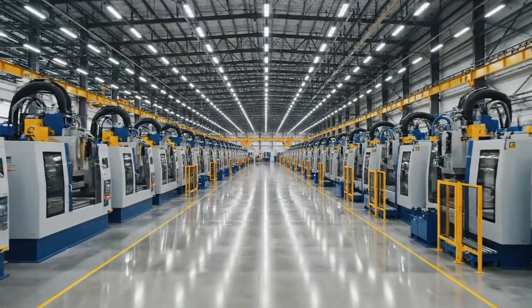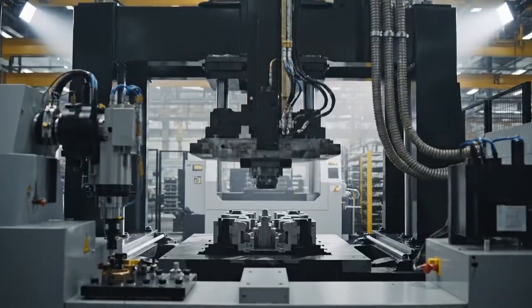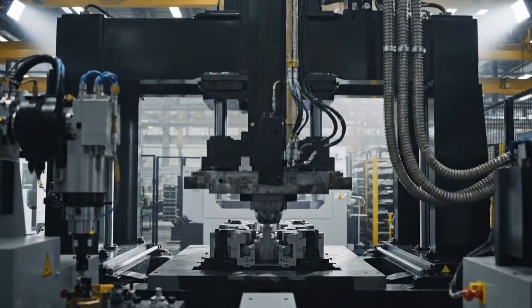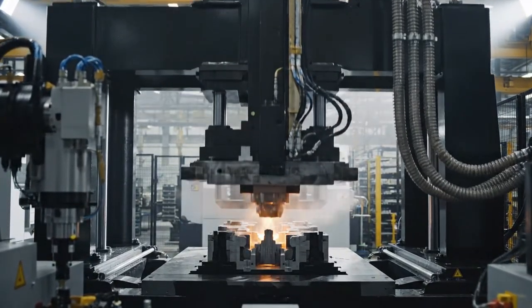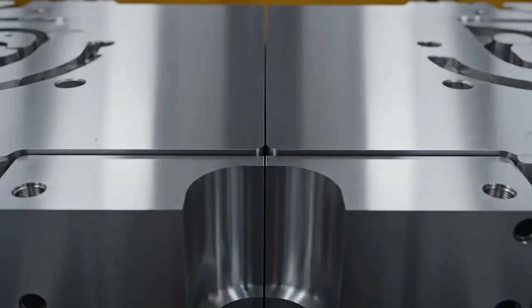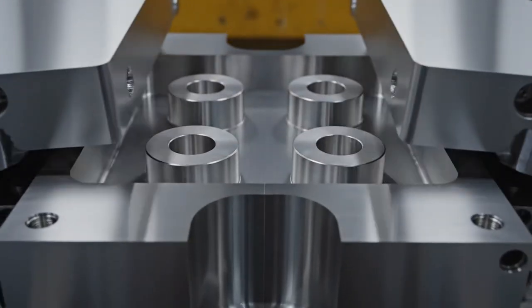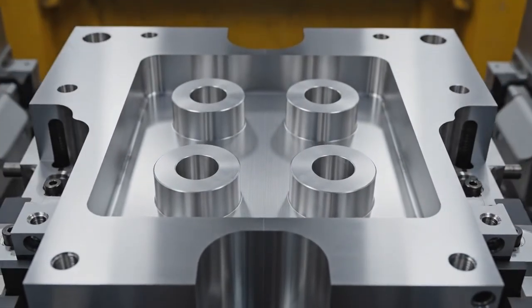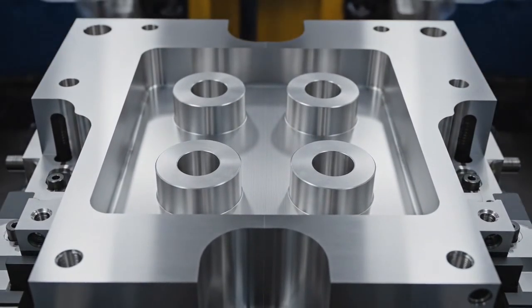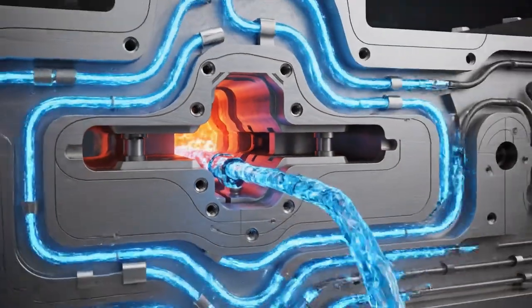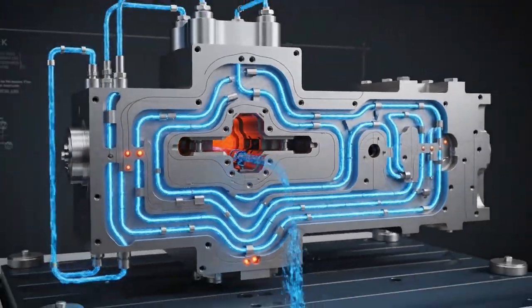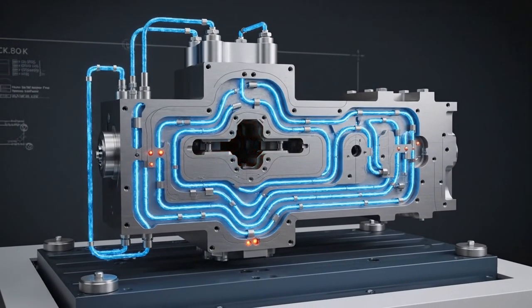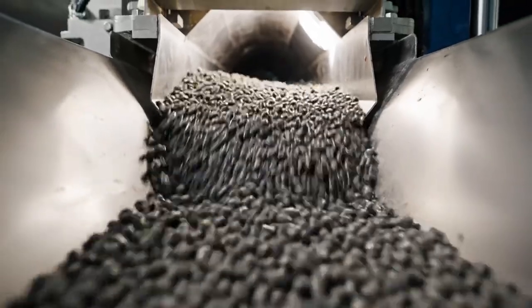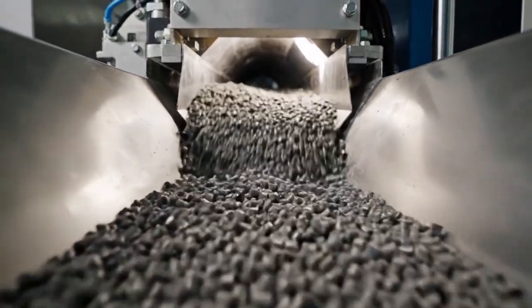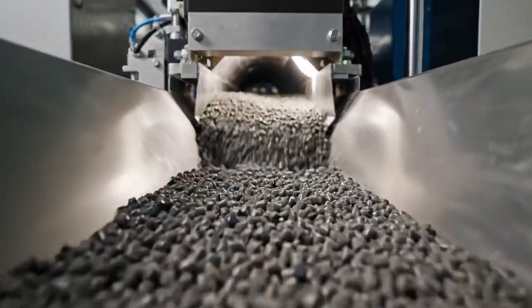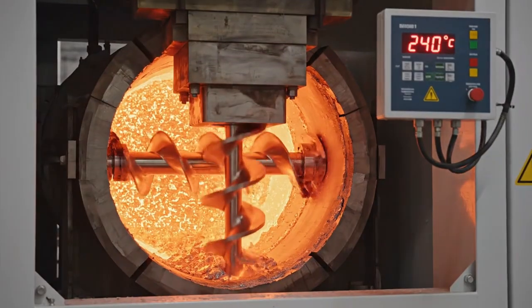The injection molding floor is where polymer becomes geometry. Rows of hydraulic presses dominate the space, each machine a 20-ton monument to precision manufacturing. The molds themselves are works of art. Hardened steel dies machined to tolerances of 5 microns, their internal cavities shaped to produce bricks with the iconic Lego stud pattern. Each mold cavity is cooled by circulating water channels, drilled through the steel in serpentine patterns to ensure even heat extraction. The recycled ABS pellets are fed into the molding machine's hopper, where they descend into a heated barrel.